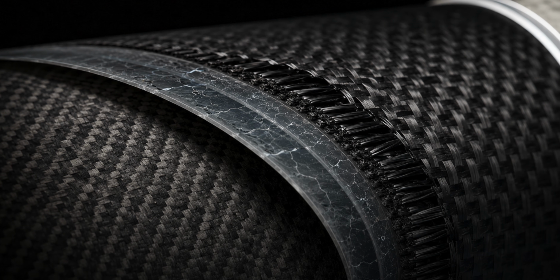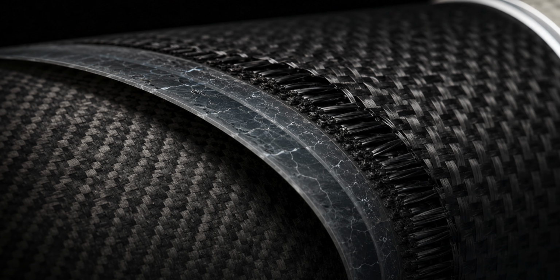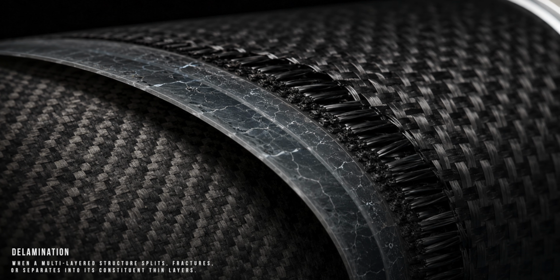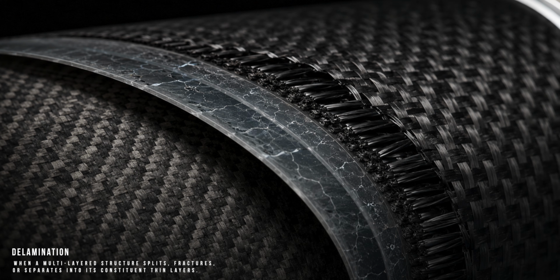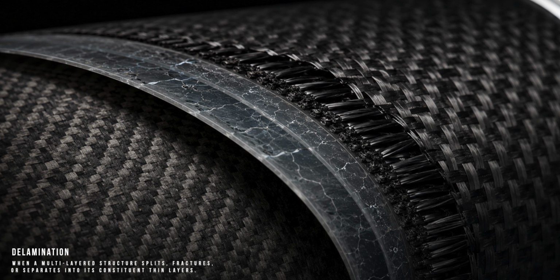While the carbon fibers provide most of the strength, the epoxy matrix is far more susceptible to microscopic cracking under repeated loading. As those cracks grow, the bond between individual layers can begin to separate, a process known as delamination, allowing damage to accumulate deep within the structure long before any signs appear on the surface.